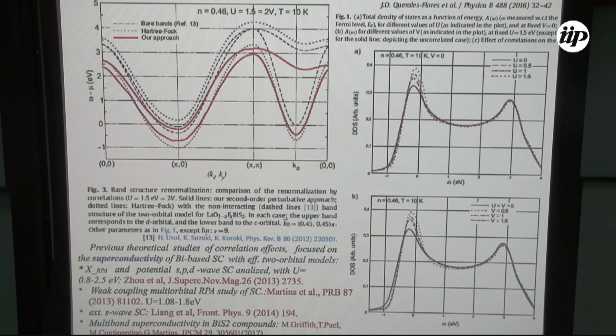But going back to the band structure, there has been actually this work by Usui, Suzuki, Kuroki, in 2012 already. From those DFT calculations, they did some downfolding and obtained the band structure, which here is shown as bare bands in black, these two curves, which are the main things we were seeing near the Fermi level in the other picture, right? And here, I already added some of the things we used to try to include the